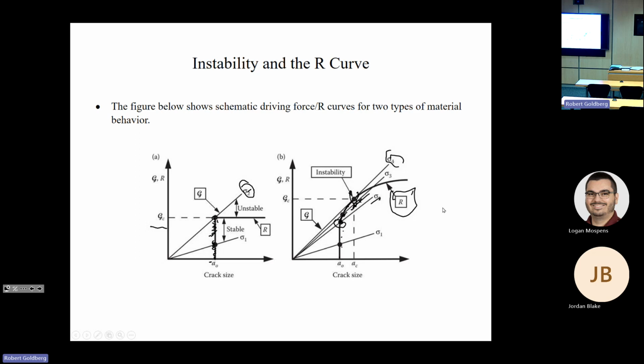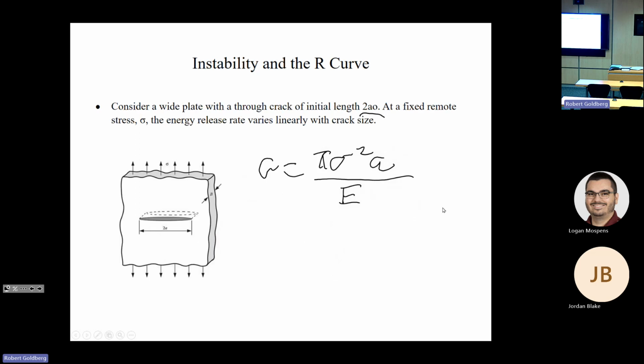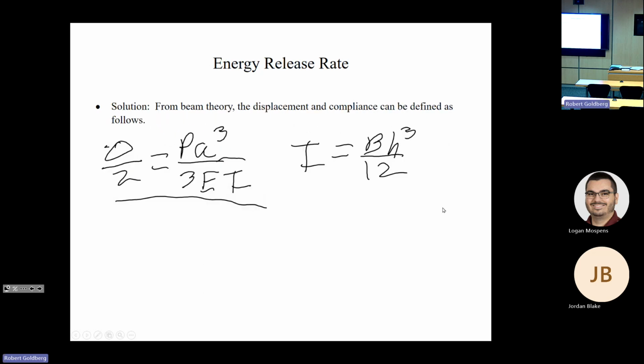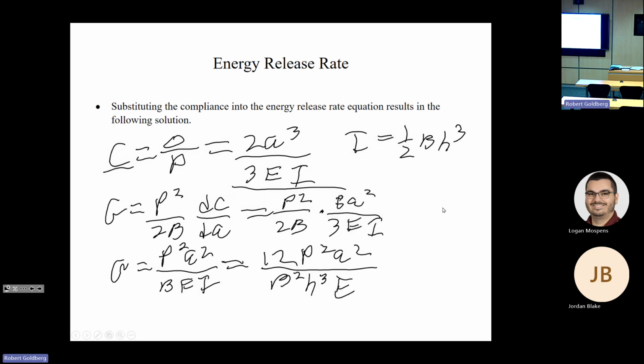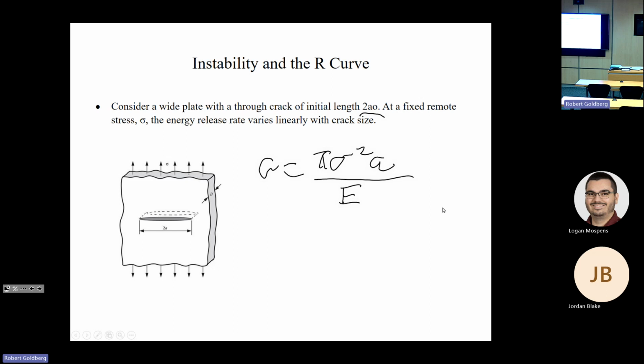So for this flat curve case, no matter what your crack looks like, when you hit this critical strain energy release rate, things fail. However, this slope of G, the curve of strain energy release rate versus crack size, is different depending on whether it's a through crack or a DCB specimen or different types of configurations. So for the through crack in a flat plate, it's linear, but in the double cantilever beam example, as we talked about in our example problem, G increases with the square of the crack size, where in our baseline equation for a through crack, G increases linearly with the crack size.